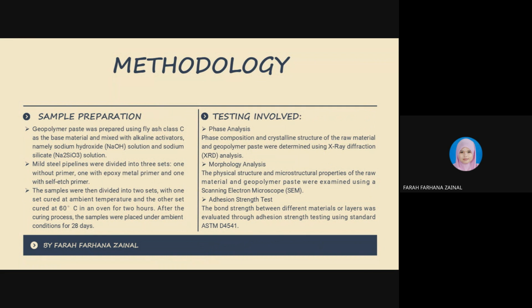And then the samples were divided into two sets with one set cured at ambient temperature and the other set cured at 60 degrees Celsius in an oven for 2 hours. And then after the curing process, the samples were placed under ambient conditions for 28 days.